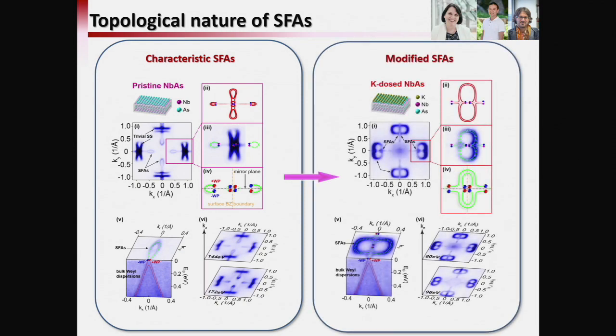And we were told also that in a topological Weyl semimetal, the surface Fermi arcs have to be connected to the Weyl points, but it doesn't tell you how to connect. So we were thinking about whether, if we modify the surface, we can reconnect all these surface Fermi arcs. And here's what we did. If we decorate the surface carefully, we were able to manipulate the Fermi arc. You can see this spoon-shaped Fermi arc become a figure-8 type of Fermi arc. So this shows the topological nature of the surface Fermi arcs.